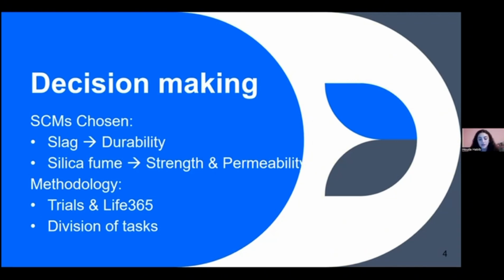When it comes to designing our eco-concrete mix, decision making was an important part of the process. We started by researching various supplementary cementitious materials like slag and silica fume, and analyzing their individual benefits. From previous experiences in the lab, we realized that slag was chosen for its durability and resistance to corrosion, while silica fume was used for its ability to significantly reduce permeability and enhance strength. We applied what we learned in the lab and, by doing trial and error on the Life 365 software, we found the most effective balance between strength, workability, and sustainability.